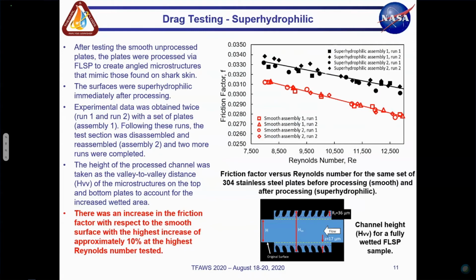As you can see on the image on the far right, the black would be the superhydrophilic. The red itself is previous smooth data that you would have seen in the Colebrook verifications. We saw an increase in friction factor with respect to the smooth surface over the whole range tested, with about 10% increase at the highest Reynolds number that we tested. We do adjust the height for a valley-to-valley distance that you can see on the bottom right.